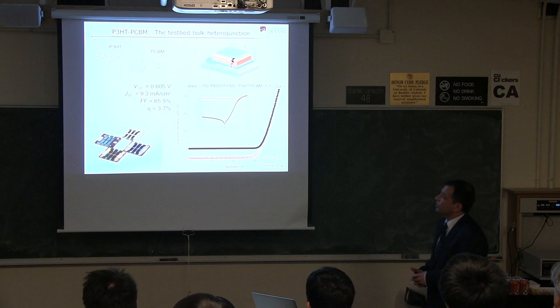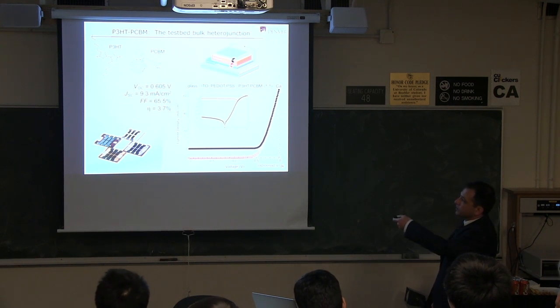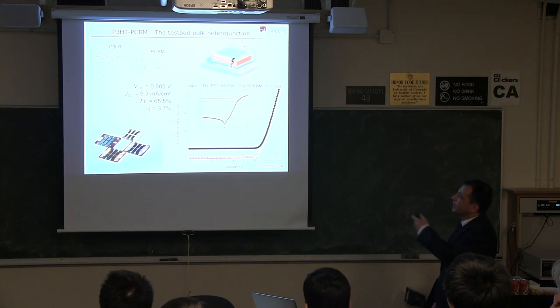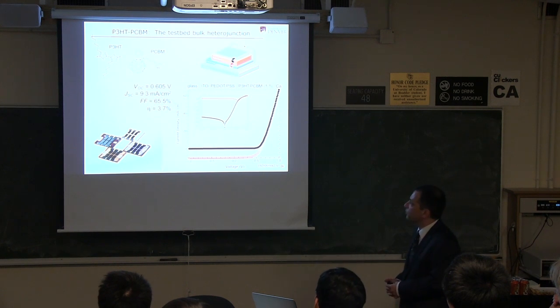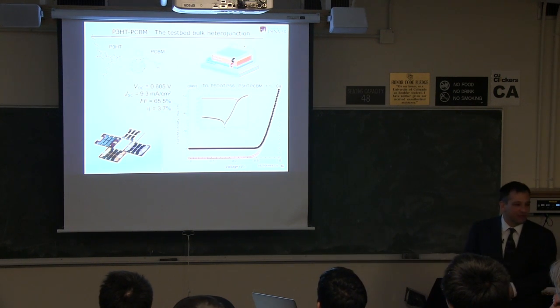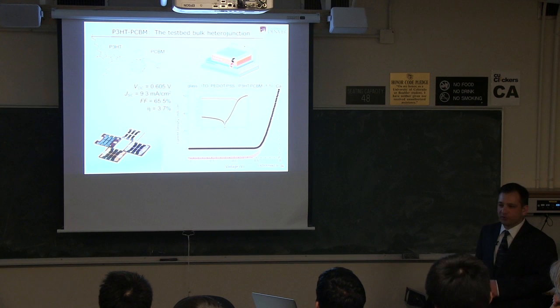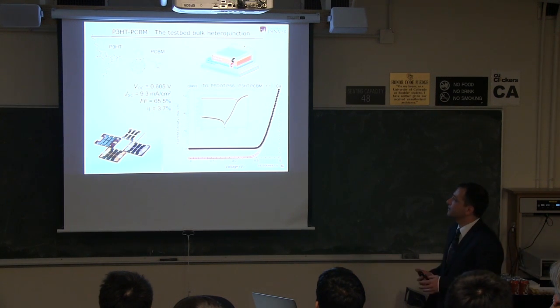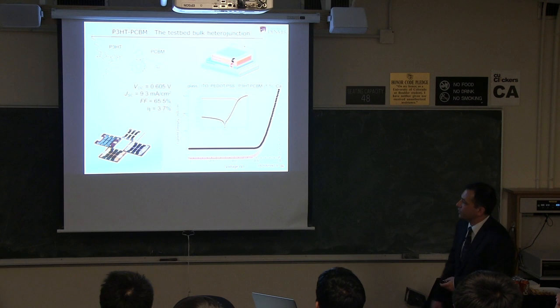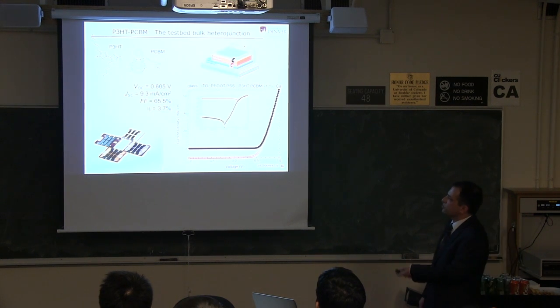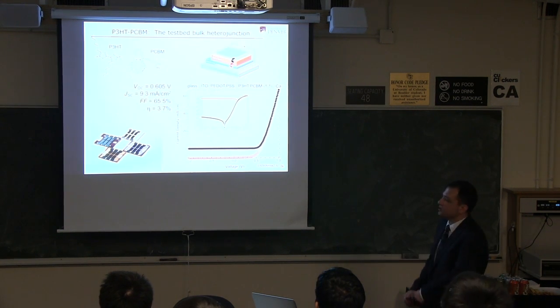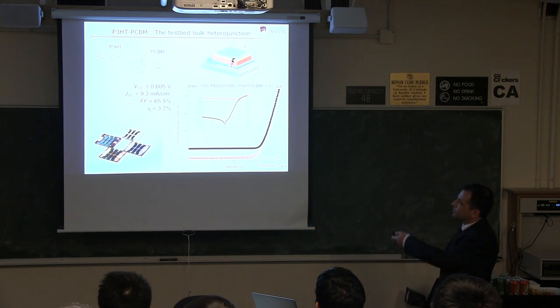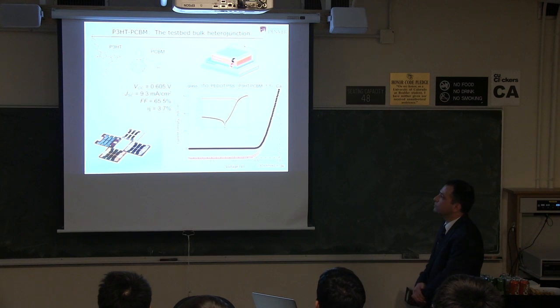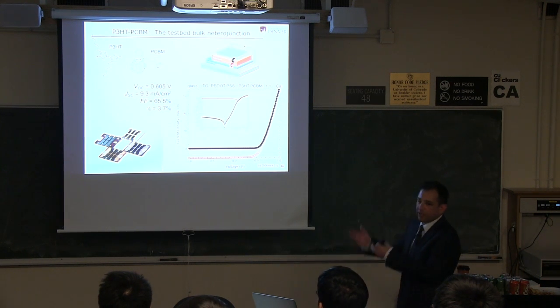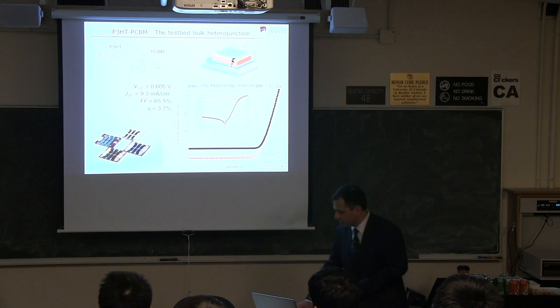So here's just a typical device. If we take these workhorse materials, P3HT, PCBM, if I took any of you into our laboratory, we could probably have you up and running and making devices in probably a day and a half. After you went through 5 days of NREL safety training, you could be doing devices in a day and a half. And you would spin cast films, and you could produce a device at about 4% efficiency pretty easily. So typical voltage, VOC of about 0.6, and typical short circuit current close to 10 milliamps, just right off the bat. Of course, we can do a lot better, but just as a typical example.